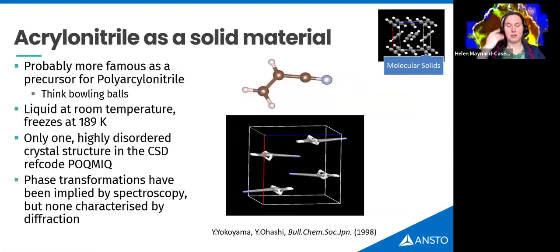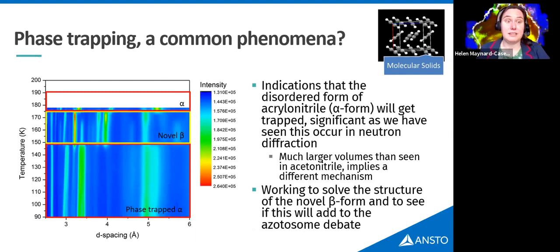And I mentioned acrylonitrile because it forms those membranes and things. We actually only know of one crystal structure of it, and that crystal structure is very disordered. And it's this that people have gone on and used to form that membrane idea. I would be a little cautious of that because you don't really understand the energy landscape around that molecule so well. And so one of the things I've been trying to do is find the ordered form of this and be able to then work out if that would impact on our knowledge of those membranes. One of the things that I've discovered as we've done this, though, is that I think we get phase trapping again.